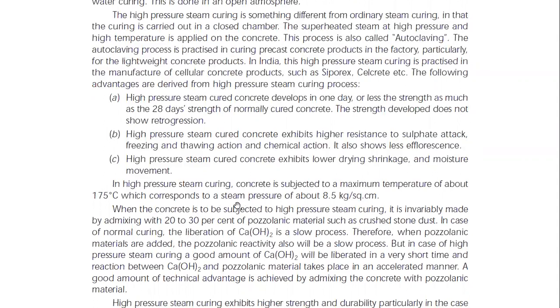So basically, in this the temperature is about 175 degrees centigrade, and the steam pressure will be 8.5 kg per square centimeter here.